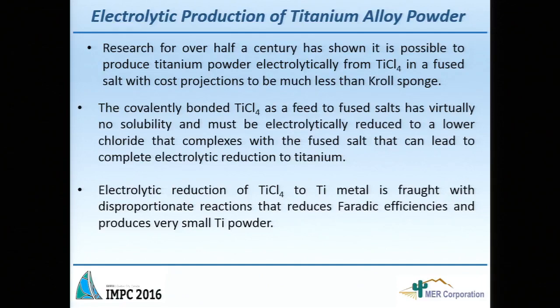And above that, it gets reduced to TiCl3, TiCl2, and then it gets oxidized at the anode because you have chlorine evolution and the chlorine will oxidize the titanium. Worse is that there's a fog formation. When you form TiCl3 in presence of TiCl4, you get this disproportionation reaction and you form titanium fines. It's almost like a mud, which is very difficult to separate from the electrolyte. And